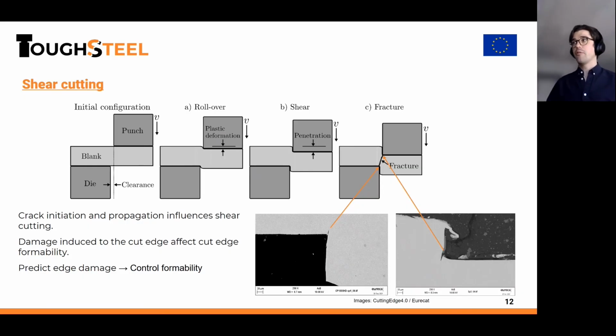For those of you who are not familiar with the shear cutting process, we can quickly look into the main steps of the process. Initially, we have a blank, a workpiece, which will be cut. Then we have a die and a punch, where the punch will move downwards and remove the right side of the blank. At first, we get severe plastic deformation and a rollover formation in the early part of the shear cutting process. Then we get penetration of the blank, where shear failure occurs at the edge of the punch. After some shear failure, cracks start to initiate and grow from the punch edges and die edges. This crack propagation is fast, and you will get a sudden fracture, and your shear cutting process is finished.